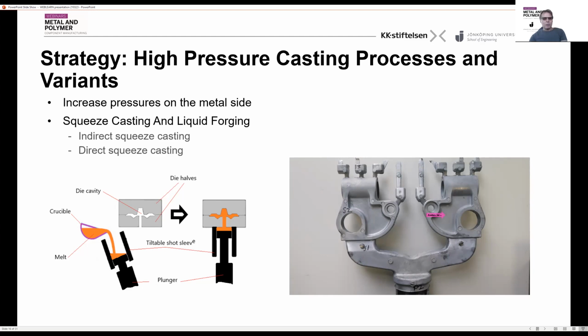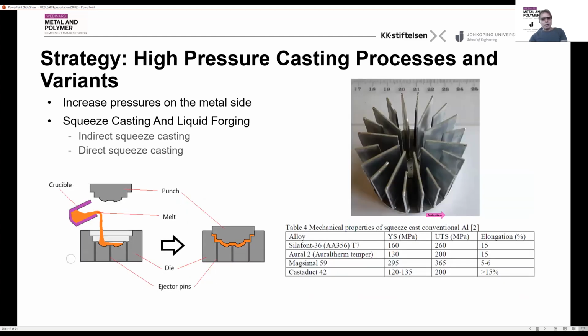So we can take the next, which is then direct squeeze casting. And the difference with direct squeeze casting is that you do not have a plunger moving the melt into the die cavity, but you pour it into the die cavity, and you have a punch from the top, just like a forging operation, where you actually squeeze the melt under high pressure. And this gives you something which is very pore free. And experience says that if you reach about 50 megapascals in actual pressure in the die cavity, you will get a pore-free structure.